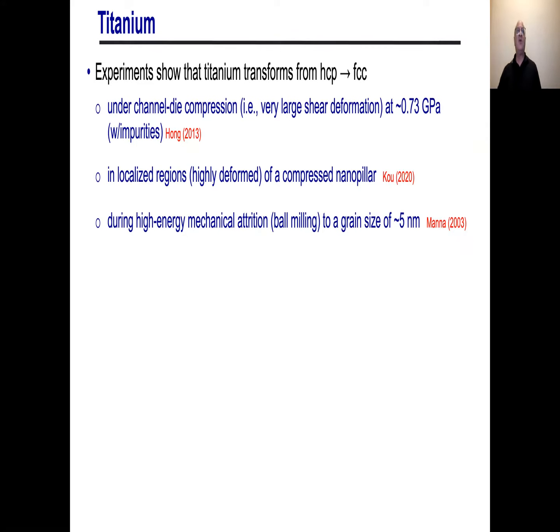in the literature. But if you look at these channel die compression experiments, where you deform material in shear, the grain size gets remarkably small, and the stresses that you can see suggest to be at least around 0.7 GPa there, and that's where they start seeing the HCP to FCC transition. If you look at a compressed nanopillar, in some regions you can see the HCP to FCC transition. And if you do ball milling, which is high energy mechanical attrition, you get grain sizes of order 5 nanometers. And when it gets that small, then you start seeing some of those grains transform to FCC.